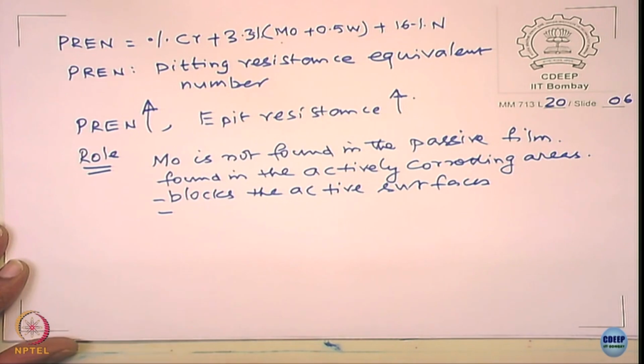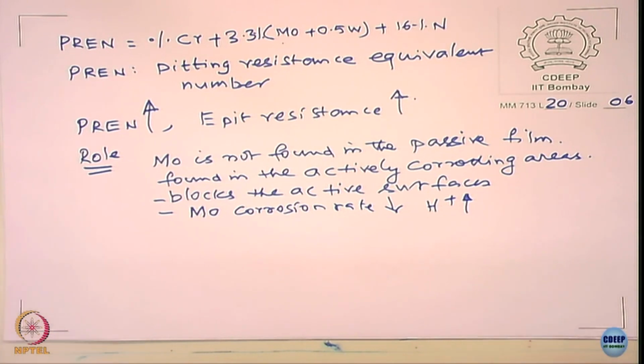That is one kind of hypothesis. There is also another hypothesis which says that the corrosion rate decreases when H plus concentration increases. It is a very uniqueness of molybdenum actually, right? You saw before, when the pH of the environment decreases, what happens to corrosion rate? Increases, right? But molybdenum has a different characteristic. When you increase the acid concentration, the corrosion rate of molybdenum decreases. This is called a negative reaction order. Suppose you have molybdenum on the surface, and if you increase the acid concentration, it is not going to corrode. Why? Because molybdenum has a negative reaction order.